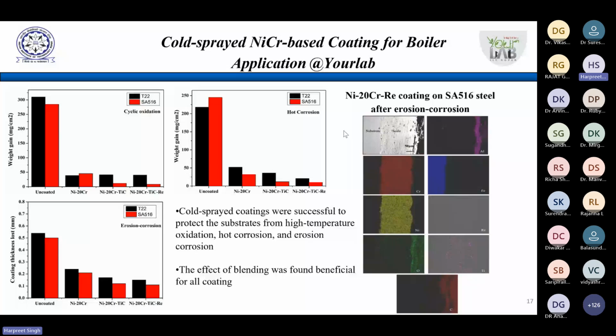But what happens is that these salts make sodium sulfate or vanadium pentoxide type of salt deposits on these boiler tubes, which will then act or react, I would say, with the protective chromium layers which are formed on the boiler tubes, and hence they will flux them. In other words, there is a loss of the protective oxide layer, and our system experiences what we call high temperature corrosion, which, if not stopped, will keep on leading to the degradation of the boiler tube wall, and one time it will happen that all of a sudden the thinning and hence puncturing of these boiler tubes can happen. So this is one thing which happens, which we call high temperature corrosion.